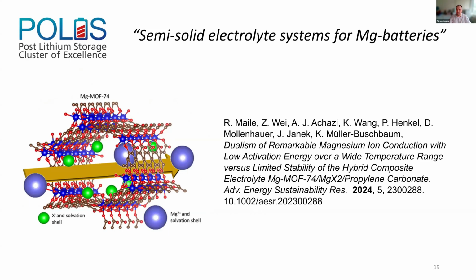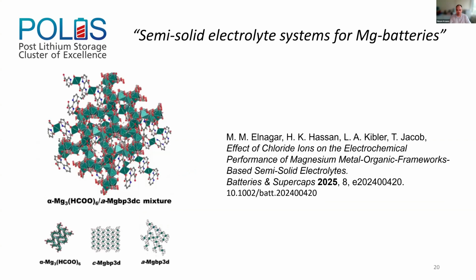Yannick and co-workers, here in collaboration with Klaus Müller-Buschbaum, were able to use a one-dimensional pore channel system, magnesium MOF-74, to reduce the activation barrier and enhance the ionic conductivity over a wide temperature range, further pushing this field of semi-solid electrolyte systems based on MOF material. And finally, very recent work now illustrates that we can further tune the MOF chemistry by incorporating heterovalent ligand systems, which also feature additional donor groups, towards further enhanced semi-solid electrolyte systems in magnesium batteries.